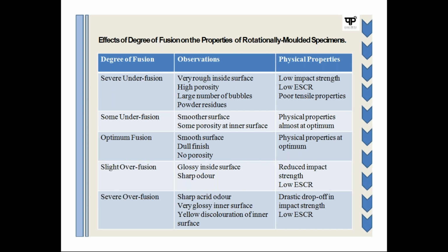In this case, with optimum fusion, you get a very smooth surface, dull finishing, and no porosity, right? So the physical properties are at the optimum. With slight over-fusion, you get a glossy inside surface. If the surface is getting glossy, you can understand that the fusion of the material has not taken place properly. That reduces the impact strength, and you get low ESCR property.